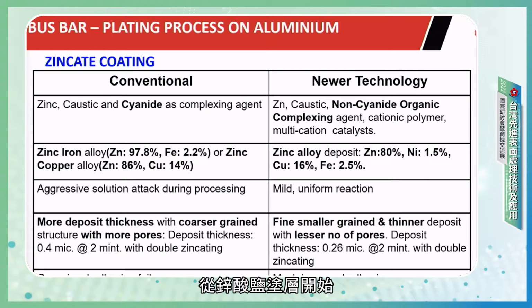Starting with zincate coating, the conventional technology contains cyanide as a complexing agent to hold the alloying elements, for example iron and copper, in solution. Because the zincate coating is in alkaline media, these comparatively noble ions like iron and copper tend to get precipitated out.